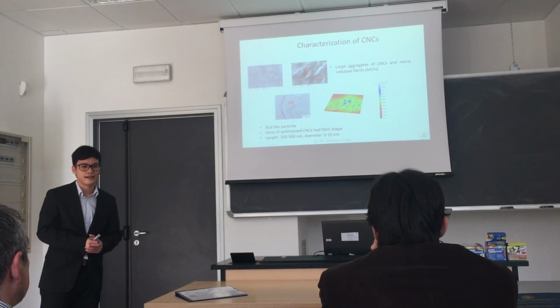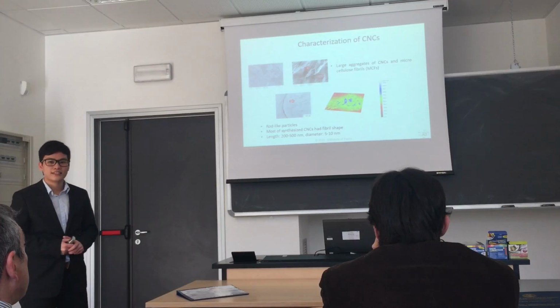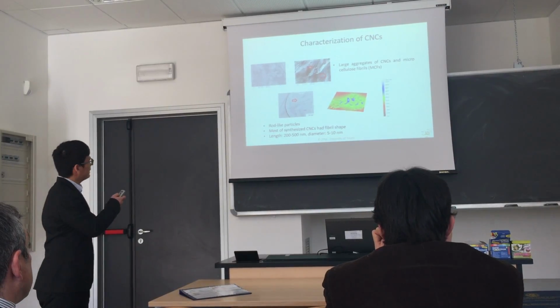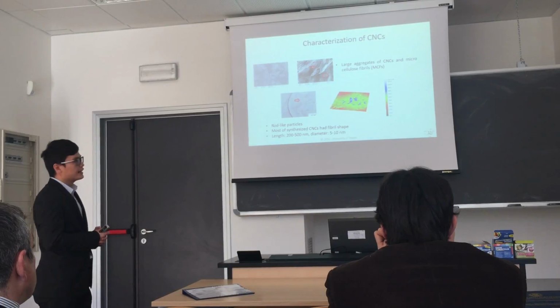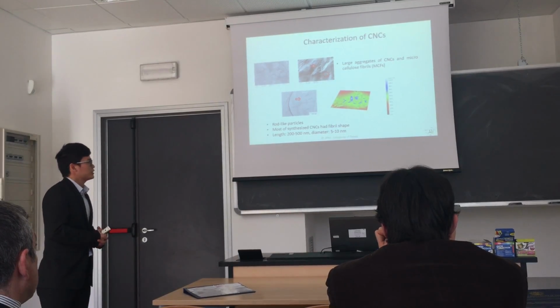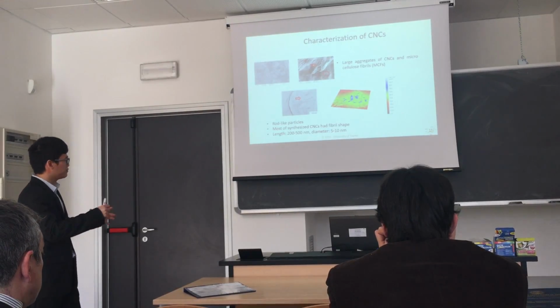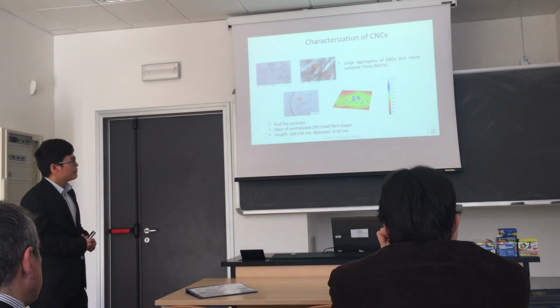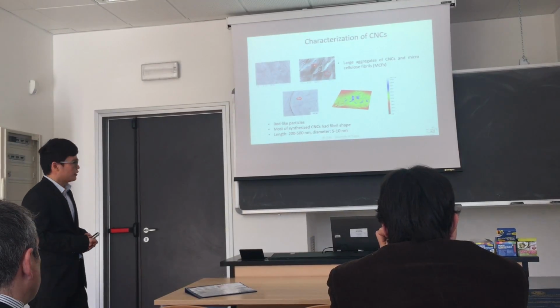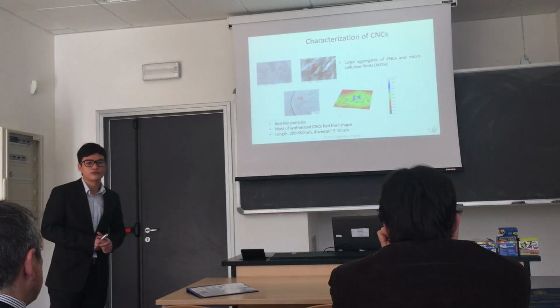First of all, I will give you some results about the morphologies and characterization of the synthesized CNC. So the SEM and TEM techniques were used to evaluate the morphologies of CNC. As can be seen from the SEM image with different magnifications, we can clearly observe the large aggregates of the nanocellulose and microcellulose fibers. Additionally, the TEM image revealed the synthesized CNC with a rod-like shape. And furthermore, the AFM technique also helped us to evaluate the synthesized CNC, which has a fibrous shape, with length varying between 200 to 500 nanometers and diameter varying between 5 to 10 nanometers.